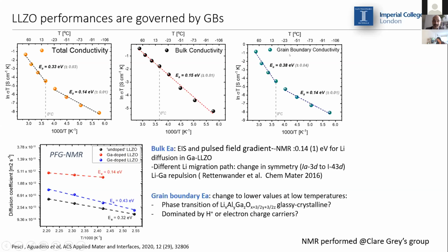However, if we look at the Arrhenius type plot for the grain boundaries, we see they also score a change in activation energy. And the total activation energy seems to follow actually the grain boundaries. So we can say that the performances of garnet are actually governed by the grain boundaries.